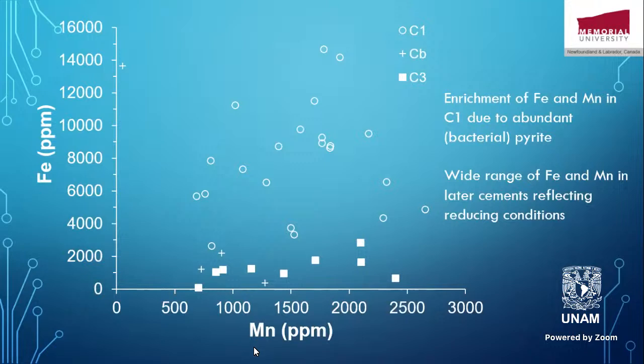We plot the iron against manganese. You can see the manganese is usually around 2000 or so, but the iron is much higher. So again, it is rich in iron, particularly for the C1 here. The enrichment of iron and manganese in C1 is due to the abundant bacterial pyrite in that lime mud. This is why, when you micro drill, you cannot avoid the pyrite there. It's hard. And this means the conditions were not that oxygenated. There were some dysoxic conditions there.